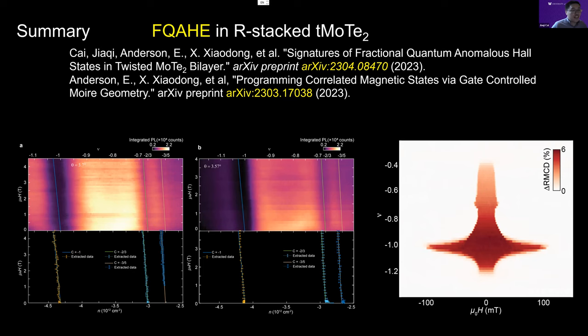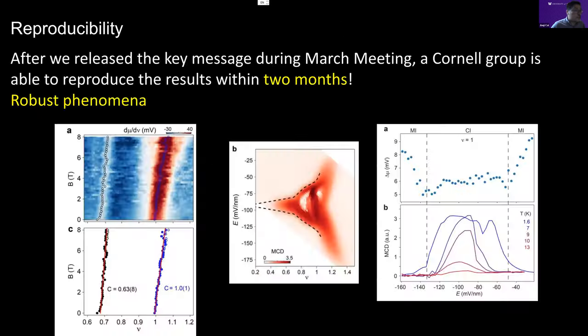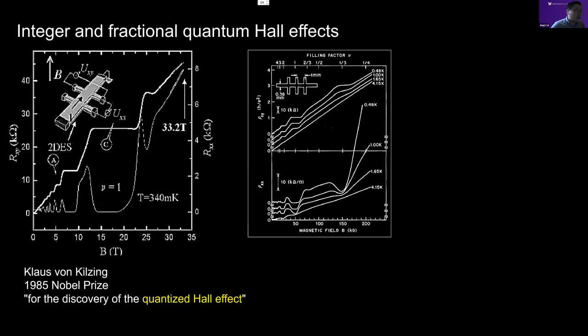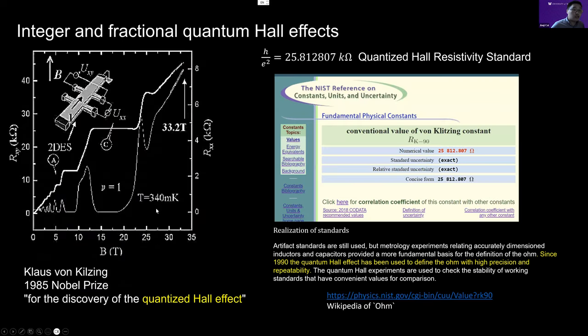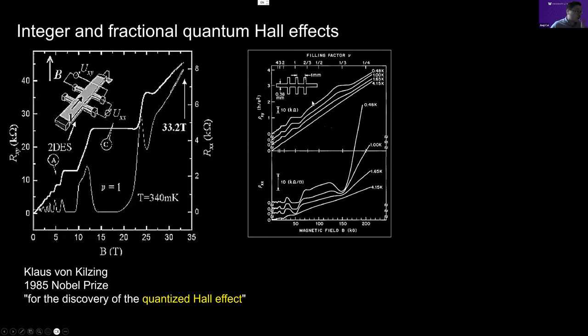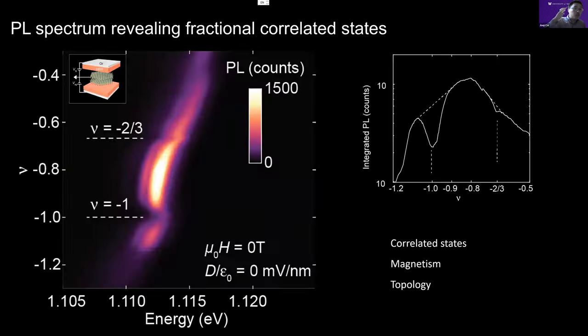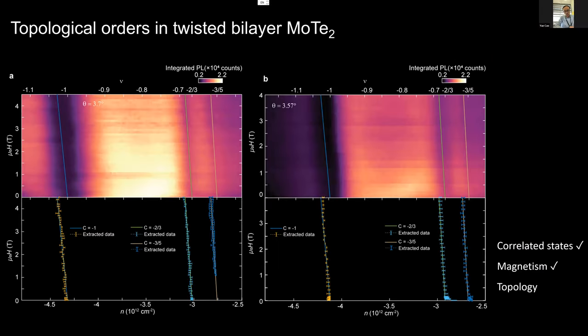Thanks. This is actually an excellent question. If you look at my introduction, the integer quantum Hall effect happens at very, very low temperature, around 340 millikelvin. For the fractional quantum Hall effect, you even go lower, down to, for example, 20 millikelvin. But in our experiment, the band gap, the magnetism, and the spin gap decide the temperature. And what we observe is that at 2 Kelvin, or helium temperature, you can already observe those fractional quantum states. So that's a big step.